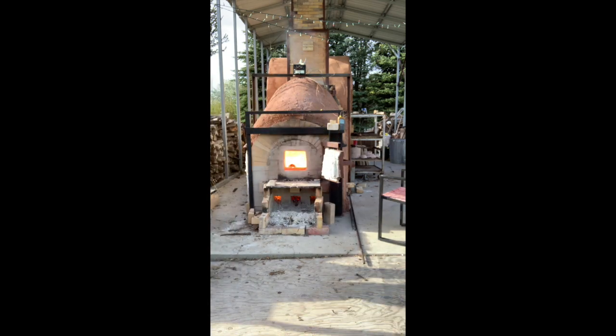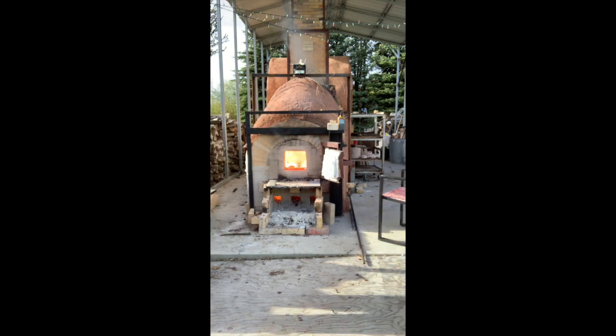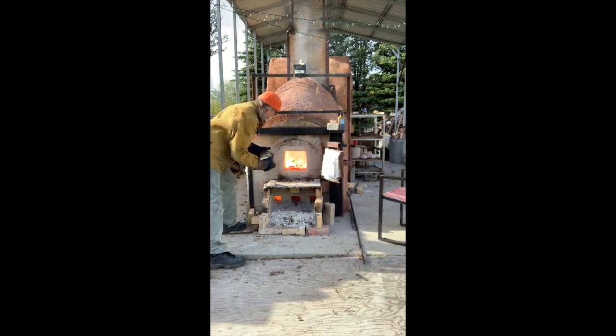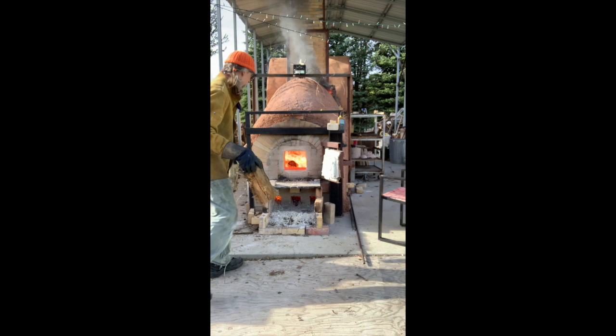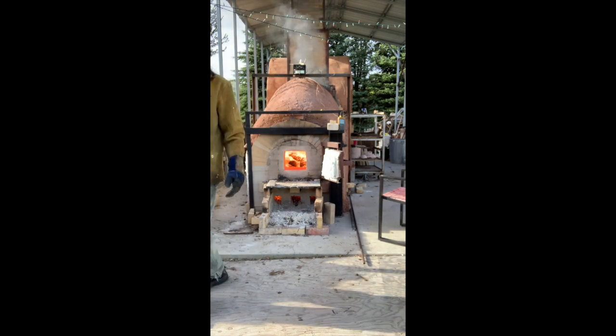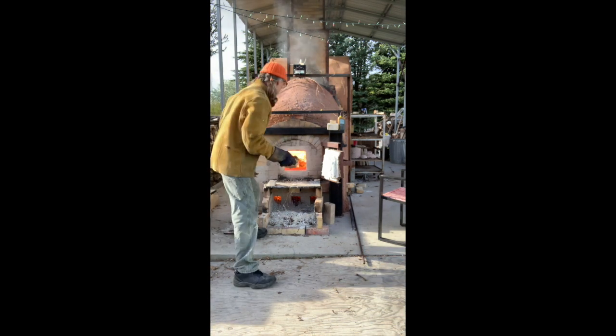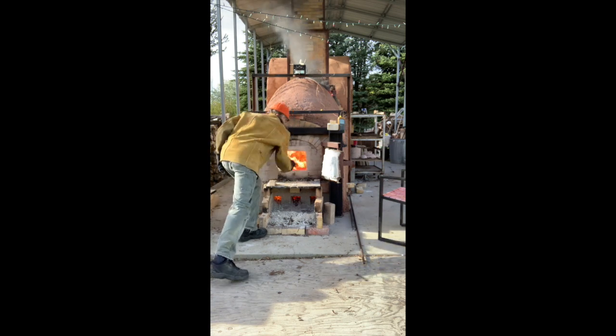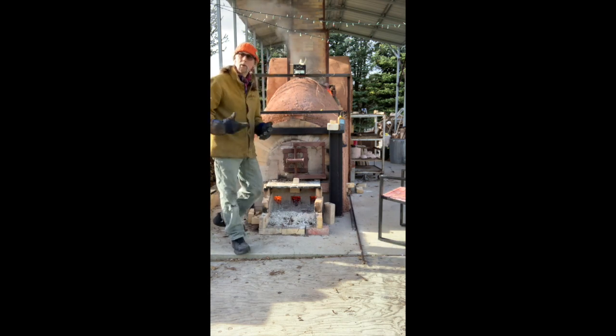I flattened all the cones yesterday, actually. Kathy was holding it all night. I was almost too tired last night, and I kind of wanted to just call it quit. But explaining to my students, it's nice to do this layering where you can cycle the firing up and down, too. We're cycling it from cone 9 to cone 11, cone 9 to cone 11, and just layering tons of ash on there so the pots will have quite a bit more.